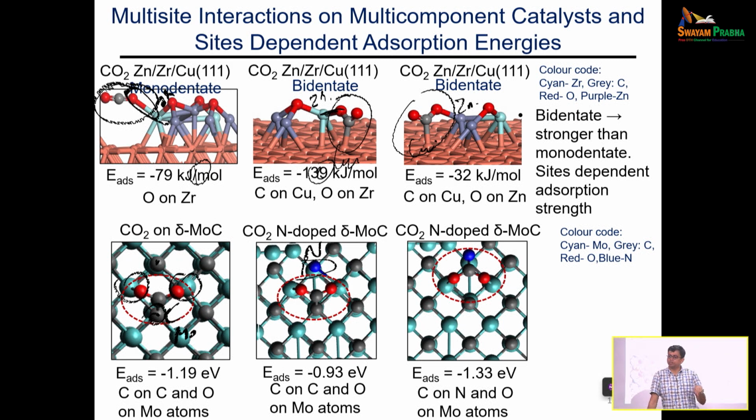Even if the adsorption does not happen on the impurity, its presence, that is what this particular middle panel shows, right. Even the mere presence on the surface changes adsorption energy so much. And what I would say is catalysis and adsorption requires you to understand the surface of your material to an atomistic scale for you to be able to comprehend what is happening in the measurements that you are making.